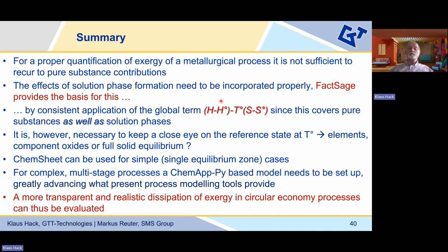And we can apply that global term consistently, no matter whether we're talking about solution phases or compounds or combinations of them. We are simply describing a particular state of a system at a particular temperature T, and we compare the very same system, and same with respect to the overall composition, at room temperature with this. And then we can apply this general equation and get consistent answers. So we do not need to work with the reference state anymore. We can use, in this particular case, chem sheet, because it was just a single equilibrium zone.